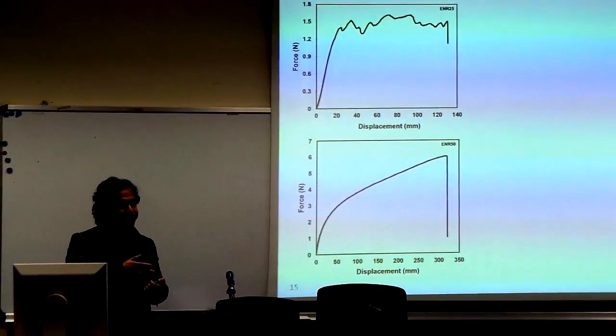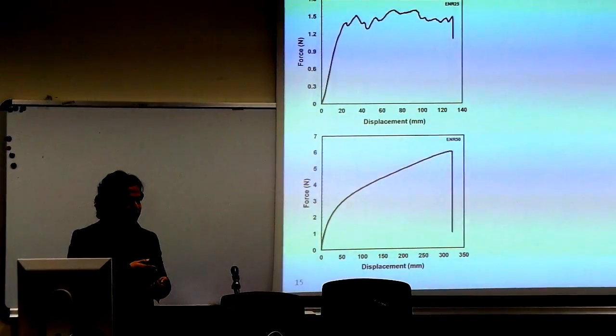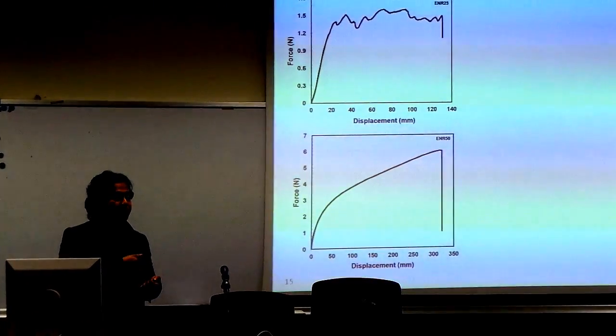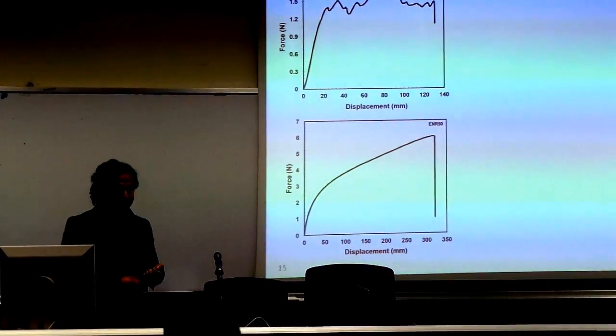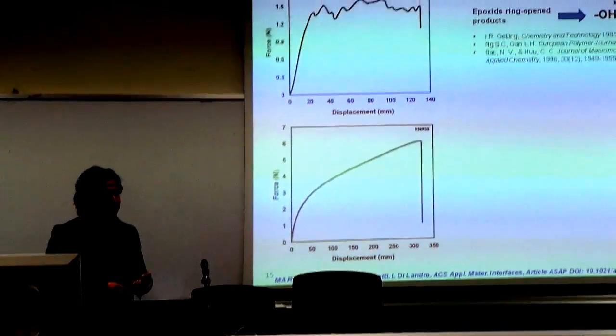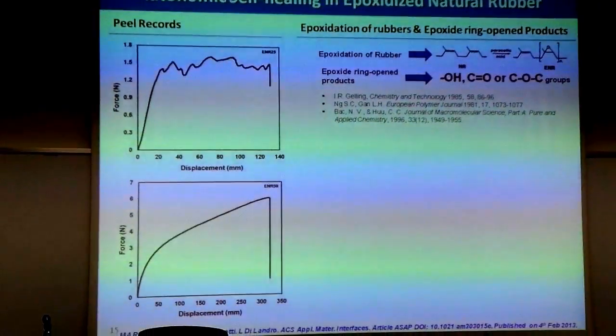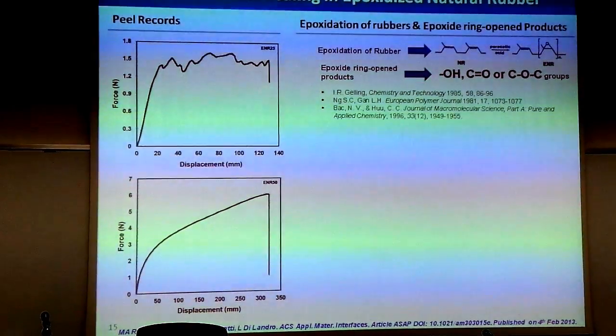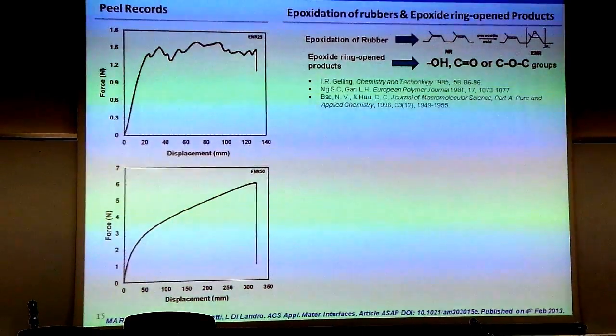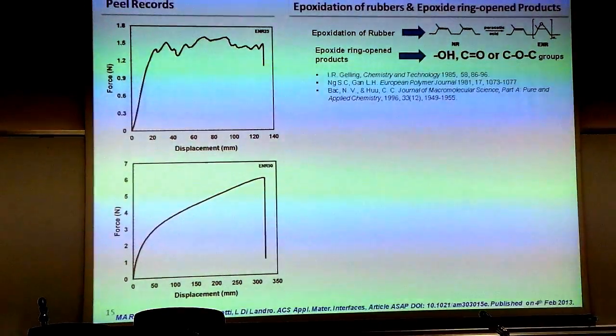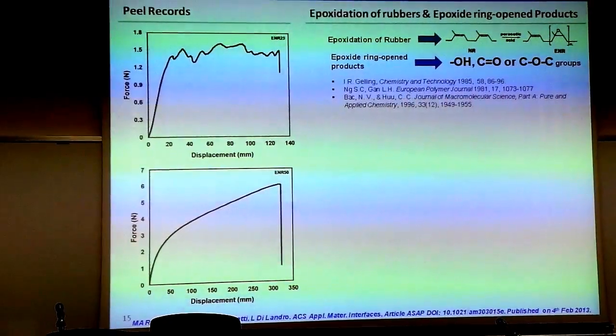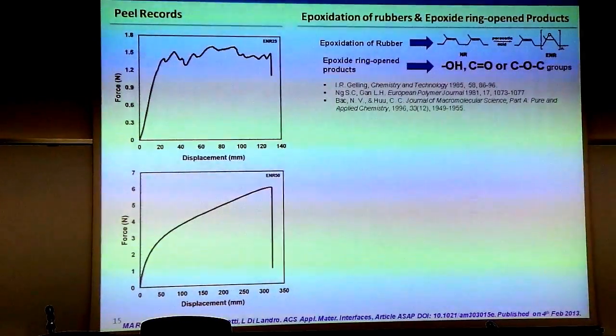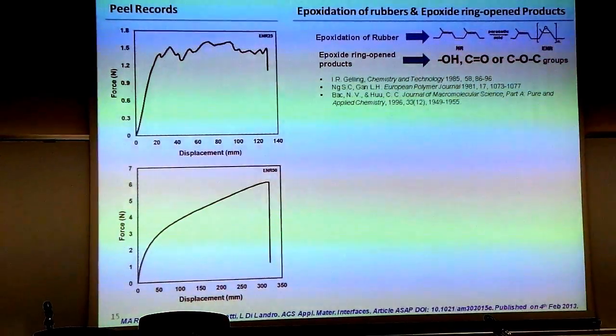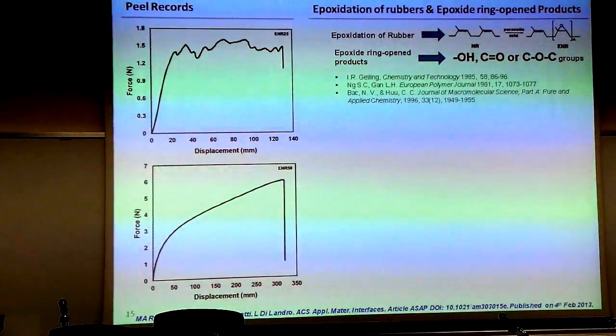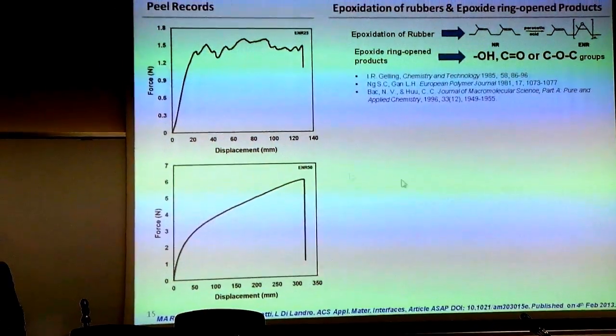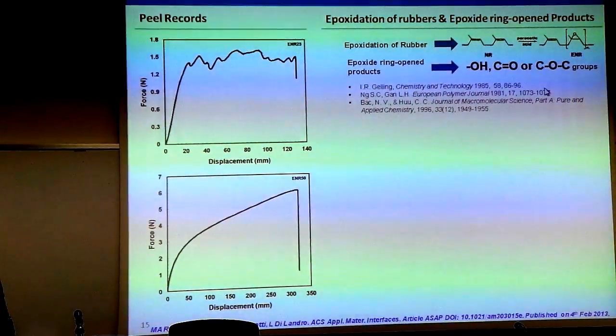I should mention here that I did not synthesize the epoxidized natural rubber in the laboratory. This was a commercial epoxidized natural rubber. But in the literature study, I found that during the epoxidation of rubber, due to the high concentration of the acid, or very low pH, or very high temperature, or even if the synthetic route is very long, it gives the epoxide ring opening products, which can be identified in the sample by the presence of hydroxyl group, carbonyl group, or ether group.